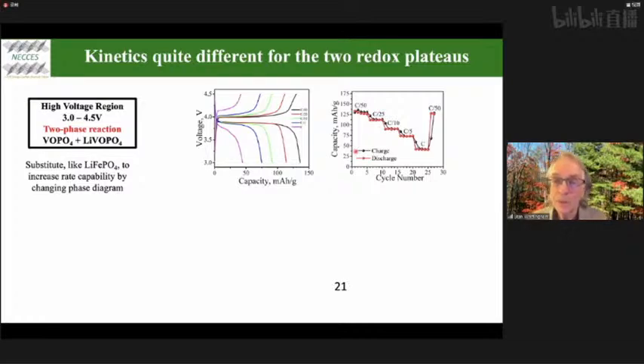So a big drop, big hindrance, but we believe we can solve this by substituting in the lattice, just like we did for lithium iron phosphate. Pure bulk lithium iron phosphate is not a good cathode. You have to either nanosize it and or substitute other elements such as vanadium or magnesium to make it work.